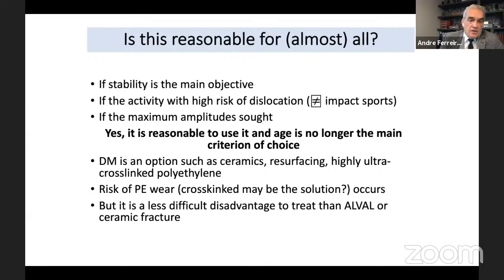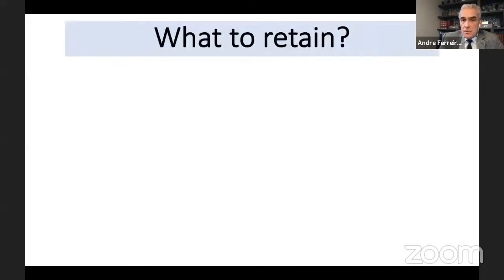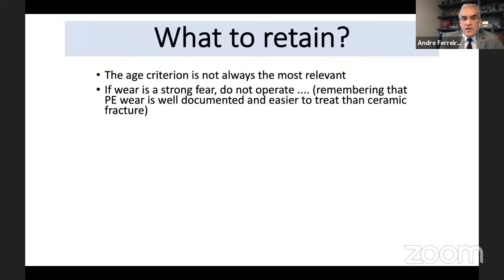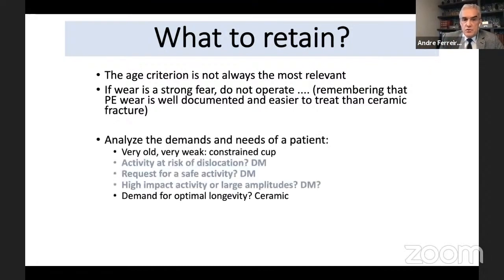It is an option, like I said before, of ceramic resurfacing or highly cross-linked polyethylene. The risk of polyethylene wear exists, but it's the same as the other options. So dual mobility is not mandatory, of course, but reasonable. What to retain? The age criterion is not the most relevant. If wear is a strong fear for you, do not operate. Remember that polyethylene wear is well documented and easier to treat than ceramic fracture.